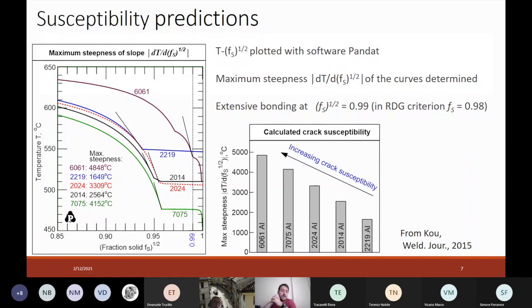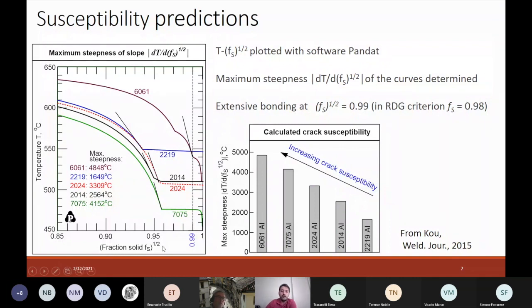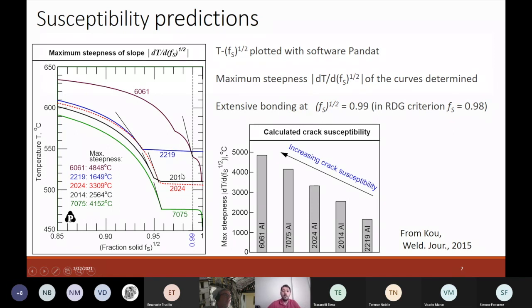Now I will show you solidification curves of aluminum alloys. These curves will be used to predict susceptibility to solidification cracking. Usually when you do the calculation for alloys, you come up with temperature versus fraction solid. You can modify it to get temperature versus square root of fraction solid. This is part of the whole solidification curve — the fraction solid starts from 0.85, near the end of solidification. After plotting this, you calculate the susceptibility index, which is dT/d(sqrt(fs)) — basically the slope of the curves.